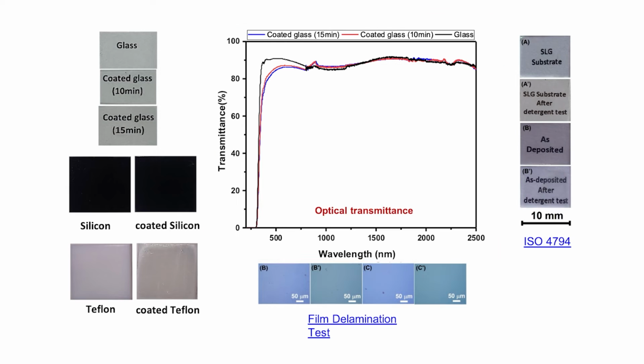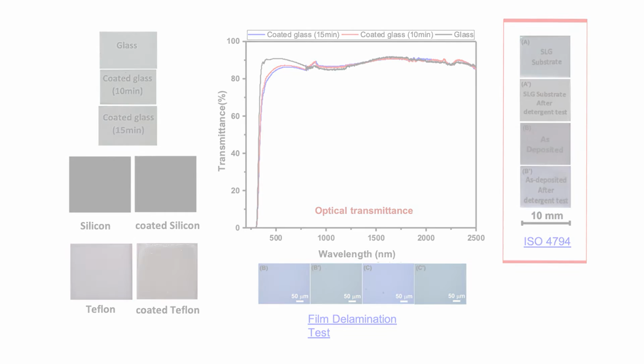We have also done the delamination test, that means using the tape test. So we found that the coating is very stable, it doesn't come out. We have also used a strong detergent test using the ISO 4794 standard, and we did not actually see much change in the color. So it says that the coating is really stable to strong detergent.